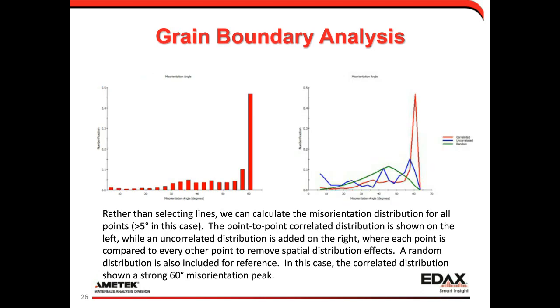And if we look at the distribution, rather than looking at a line, we look at the misorientation distribution for all the points. Greater than 5 degrees in this case, I'm going to filter out those low-angle misorientations from plastic deformation. But we're going to look at the point-to-point correlated distribution. We see that on the left. We also see it on the right as the distribution in red. We also look at the uncorrelated distribution, and then we also show a random distribution.